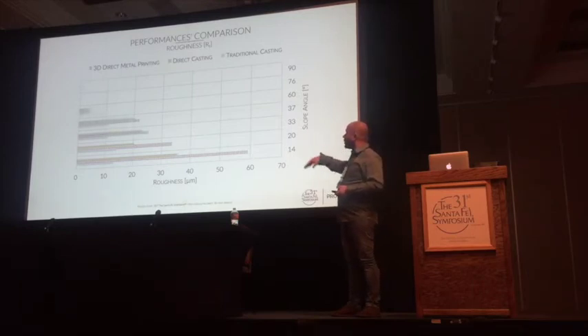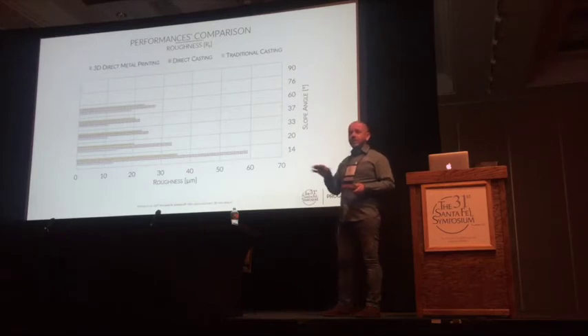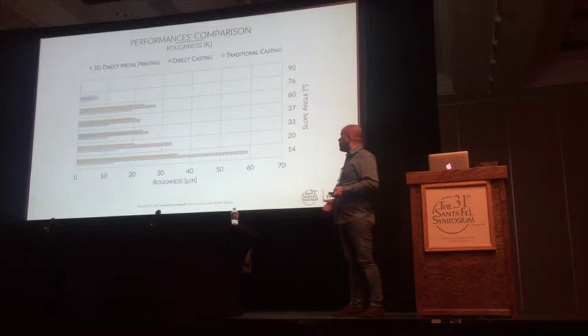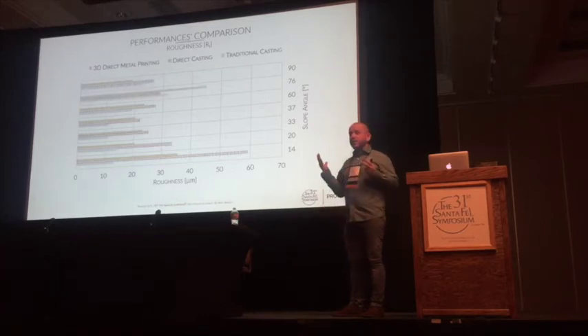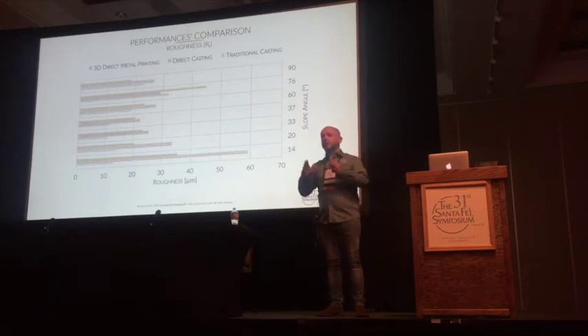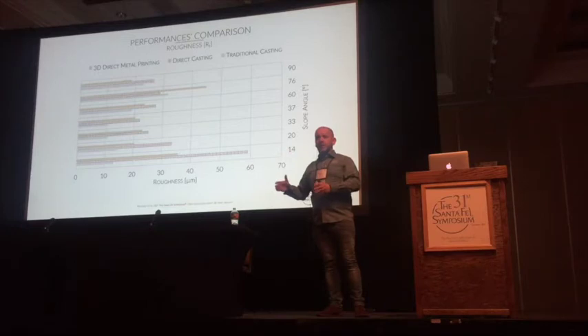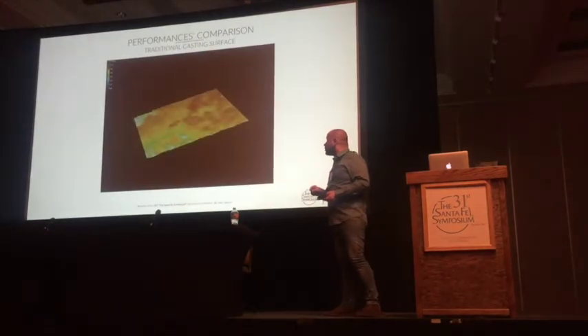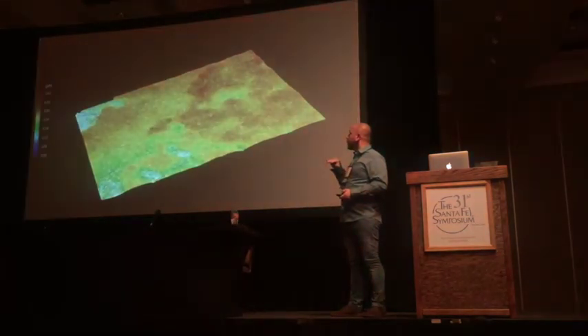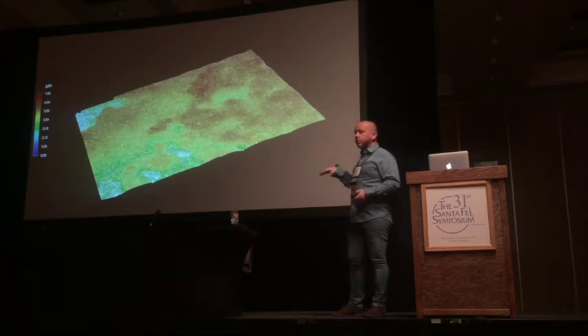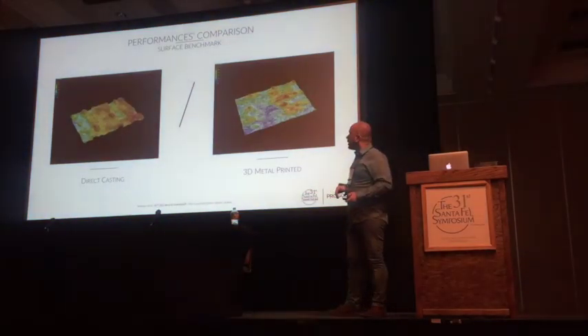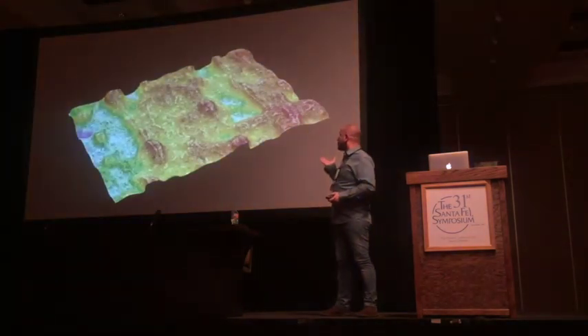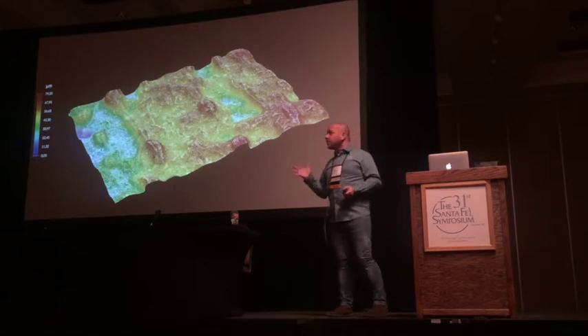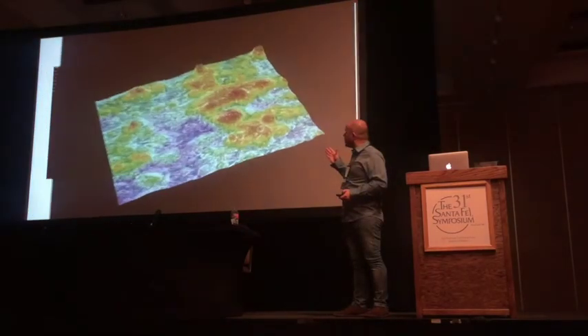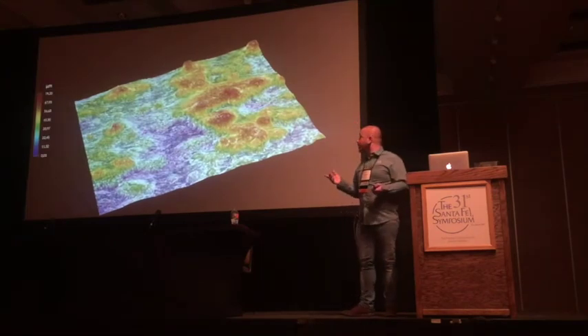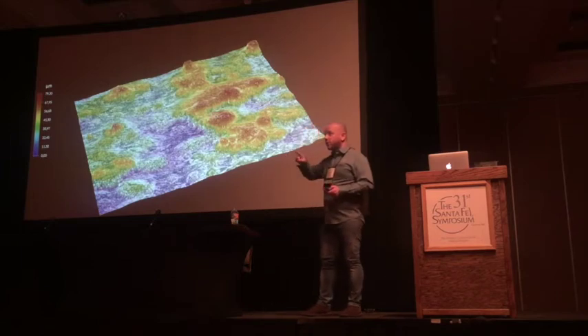I changed the graph, because the light was not so nice and the colors didn't work well last night. So I hope you are able to see the difference. What I want to tell you with this slide is that the roughness is not much worse than direct casting. We prove it with that 3D image of the surface. This is traditional casting, so very smooth. Look at direct casting. The pictures are at 500 magnification. You watch the 3D metal printing, and you see that it's not much worse. It's similar, okay?